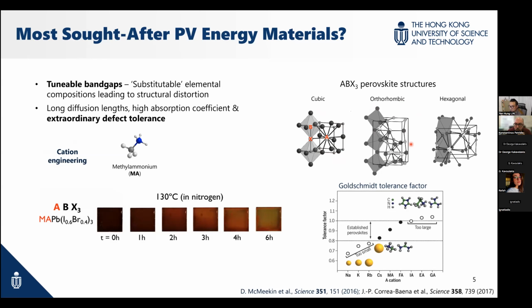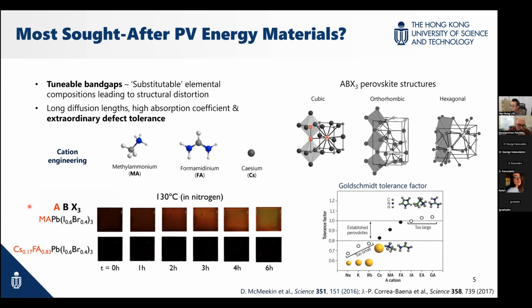Maybe. So this is just an example. We use methylammonium-based perovskite materials as compared to this kind of mixed cation, cesium formamidinium, I just talked about. And we simply age the perovskite film in nitrogen at 130 degrees Celsius. You can see it changes color for methylammonium-based perovskite because it simply decomposes. It loses the perovskite structure.